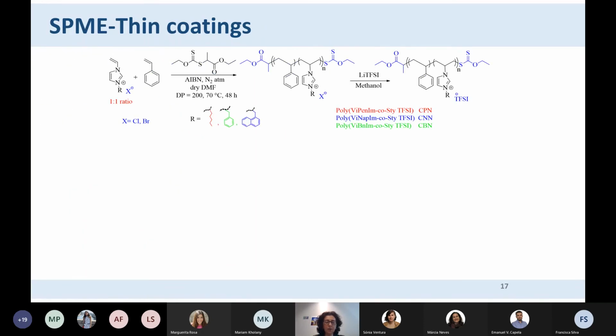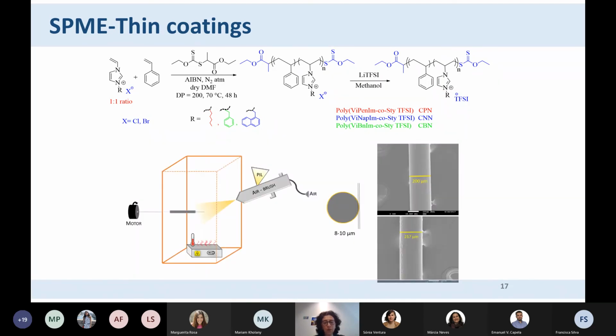However, these fibers were not what we had in mind because they were too thick. We saw that we let the fibers sorb, and it took a long time for them to sorb and to desorb. And so we decided to do thin coatings. In the thin coatings, this was a collaboration with India. We had a project with India on this, again with an organic chemistry group.